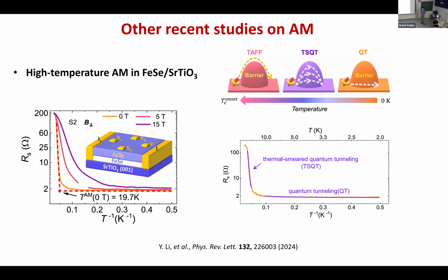I think so far there is no agreement on the theory, precisely, about the anomalous metal phase. So one proposal is they claim that it's about the vortices. Think of the system as some randomly connected superconducting puddles, and then the vortices can jump around when you apply some field, but you have to cross some barrier at high temperature. But when you go to very low temperature, then you go into a regime where the vortices just tunnel through this barrier. So because of this fact, you do not have a very strong dissipation. However, when your vortex moves, actually it generates some resistance, it generates some voltage. So this is one theoretical picture to understand the anomalous metal phase.